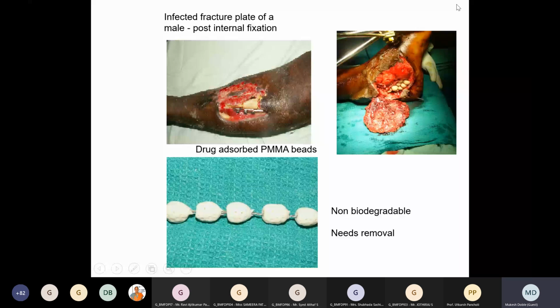Whereas by keeping drug-loaded polymethyl methacrylate beads close to the wound area, you get a high local concentration. So the wound is quickly healed, and the bacterial infection is also under control. But the main problem with this polymethyl methacrylate is it's not biodegradable. Once the drug gets released, say over about 10 days, which is a crucial time that keeps biofilm formation, bacterial adhesion and infection under control, after that the body will take care of healing the person.